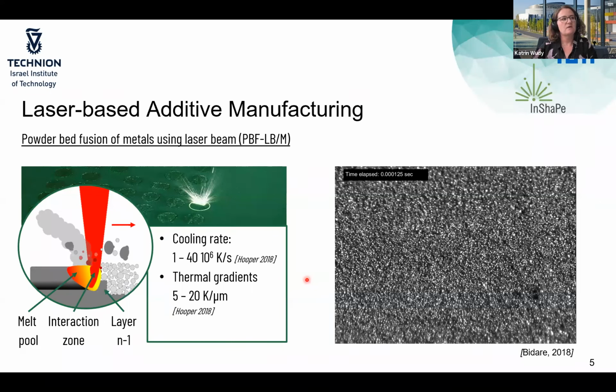What you can see is, if you change the beam profile to a ring-shaped beam profile, you can increase the process window, and you are also able to conduct higher process speeds and higher laser powers at the end. Nevertheless, you create a quite stable melt pool. This is something we already published in the paper you see at the bottom.